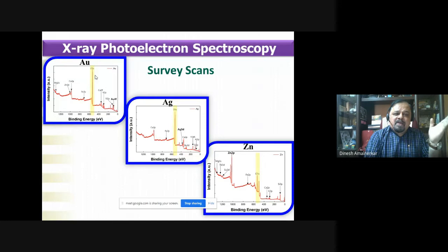Obviously, you can't expect any atmospheric oxygen to be detected by this kind of analysis. So what is this? Zinc we can expect, because zinc oxide formation is already confirmed by X-ray diffraction. But X-ray diffraction does not agree with the formation of any oxide. So what could it be? Is there any mysterious bonding between the gold and the atomic oxygen in Swarnabhasma, or mysterious bonding between the silver and the atomic oxygen in the Roupyabhasma or Jasadbhasma, whatever we can call it?